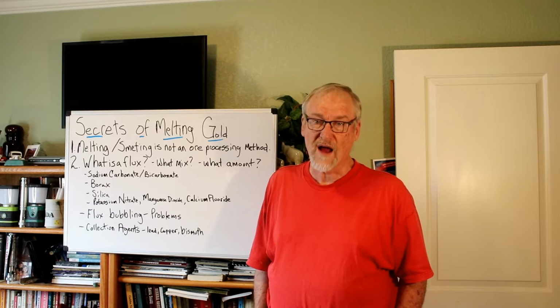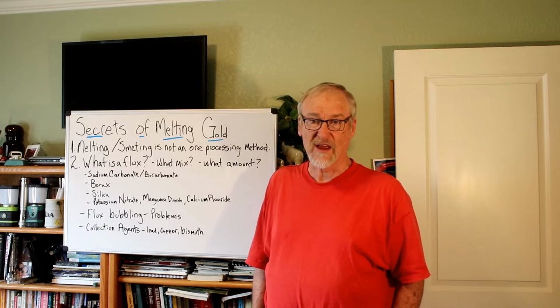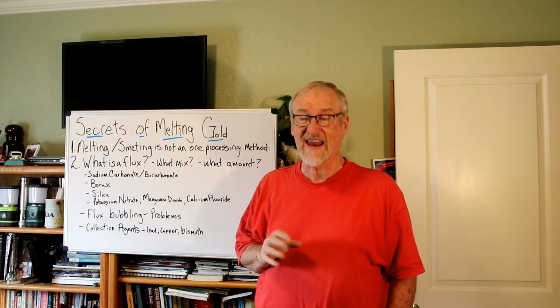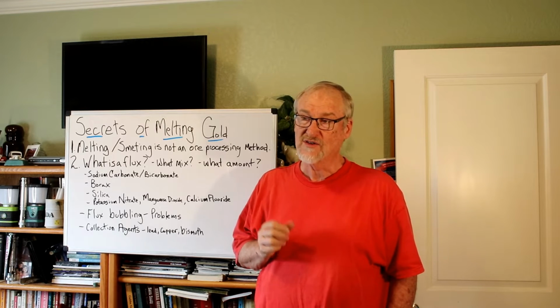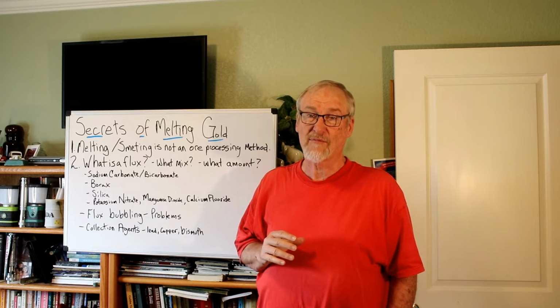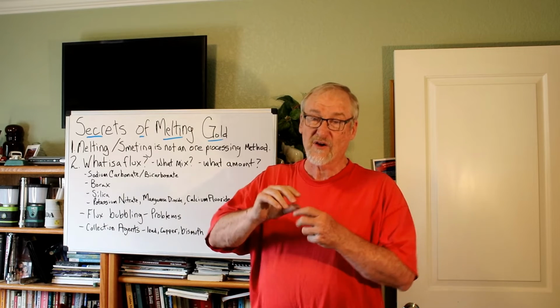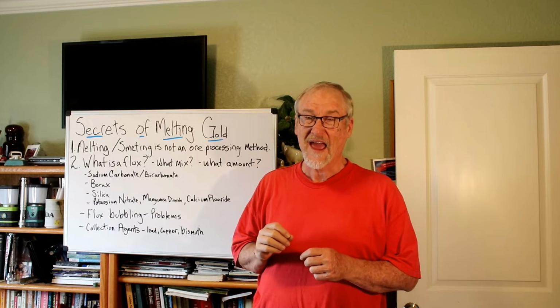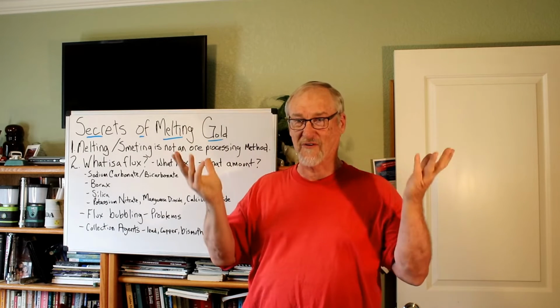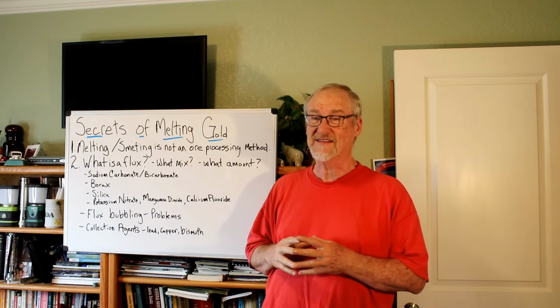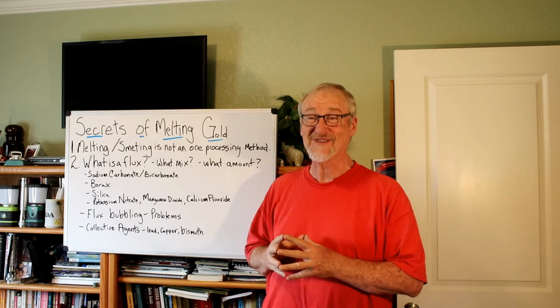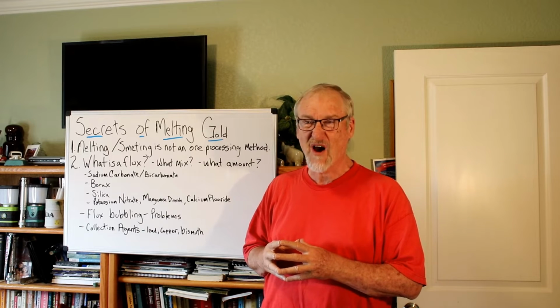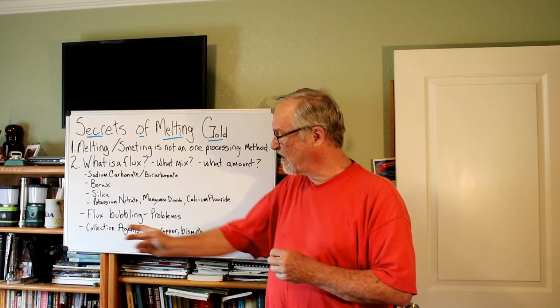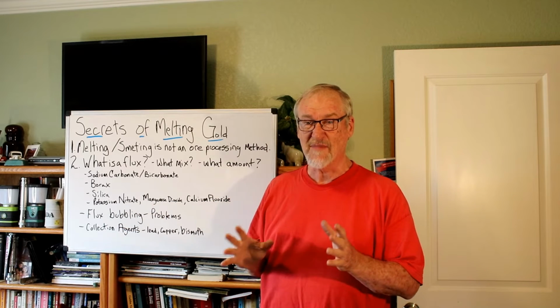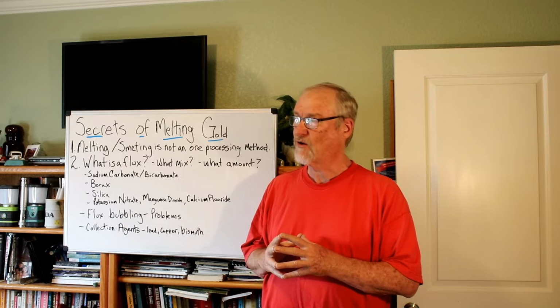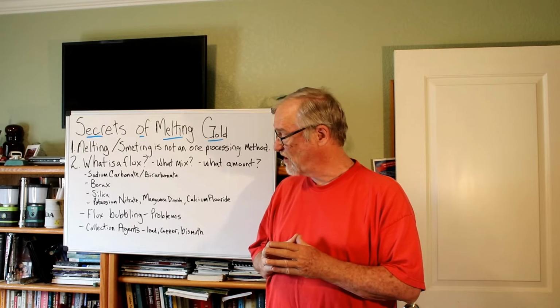So you don't want to spill. You don't want to have bubbling problems. And one of the things that you do to deal with that is have a plenty large enough crucible so that if it bubbles a little bit, you're not going to have a problem. Sometimes newbies will fill a crucible right up almost to the top, and then when it melts and bubbles, poof, over the top it goes because there's no extra space in the crucible. So always leave some extra space in your crucible, because you almost always get some bubbling. Depending on if you add these oxidizers to the mix, you're going to get more bubbling. And so be prepared. Be careful, know what you're doing.